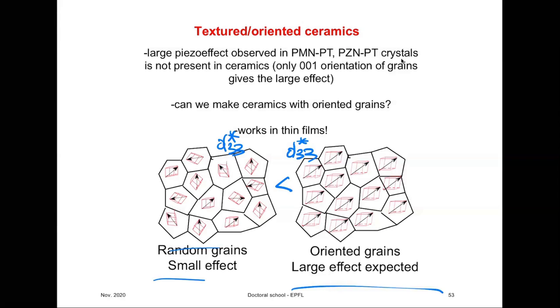Here, in ferroelectric materials, you would still have to pole material to get a maximal response, and that's because you would have some domains. So if you take this case here, for example, some of these polar vectors could have been oriented like this or other directions, or some of them like this and some of them like that, and we would still need to polarize material.